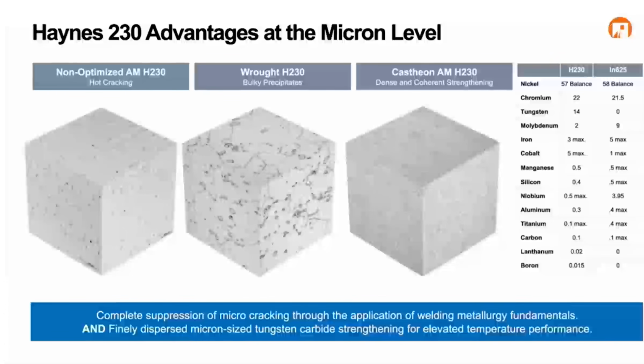Looking in the middle there, you can see Haynes 230, this nice 3-dimensional representation of the microstructure and the various orientations. You can see these large tungsten carbides forming at the grain boundaries, which is going to limit your suitability at high temperatures over time, especially in creep performance as it's subjected to constant load.